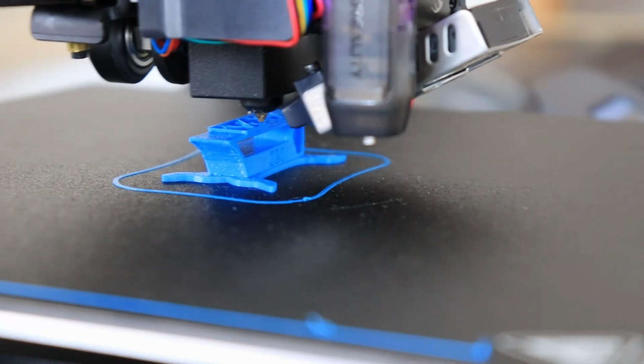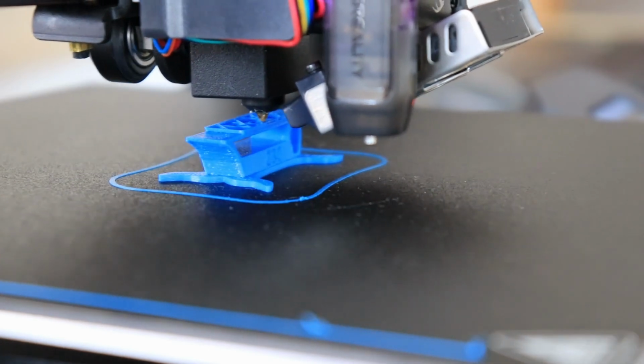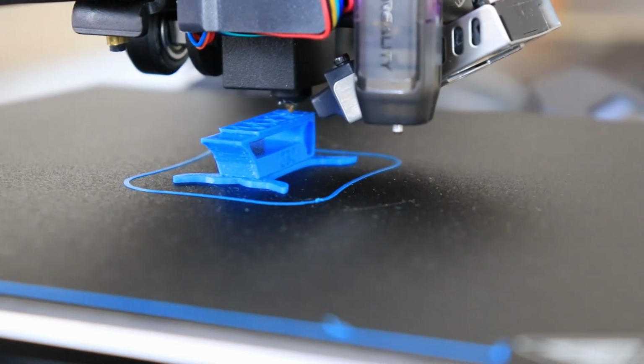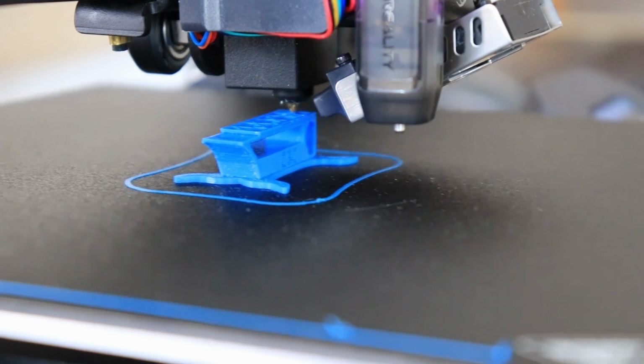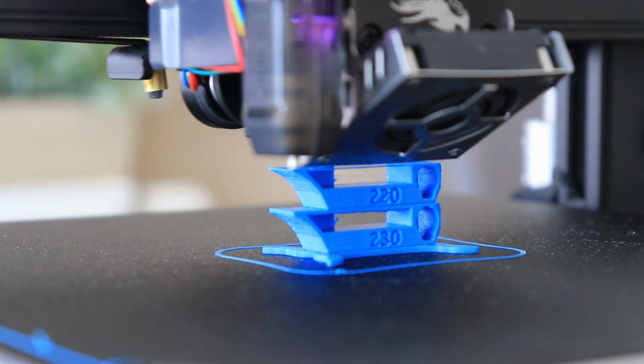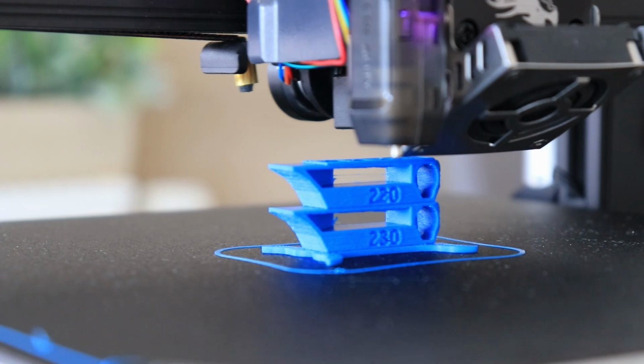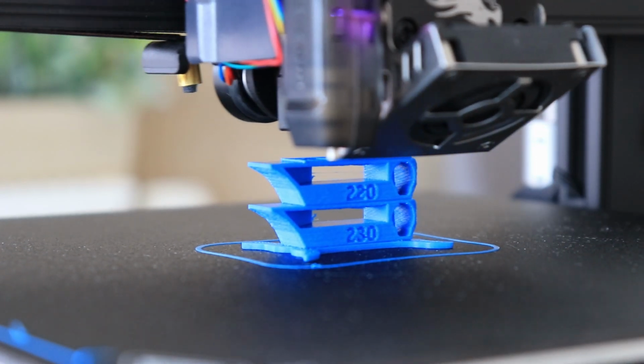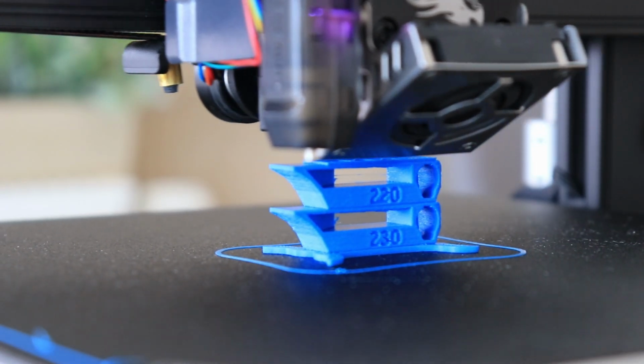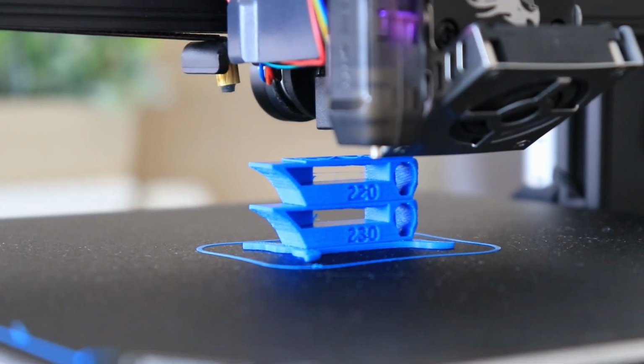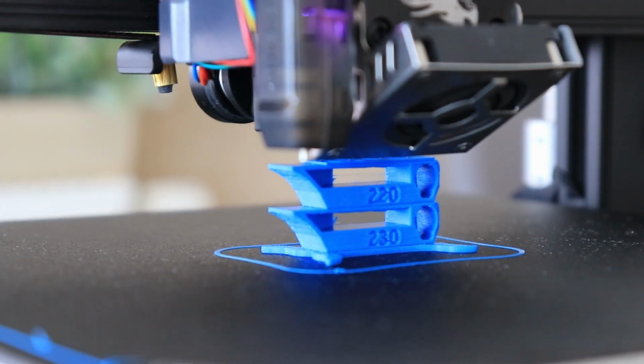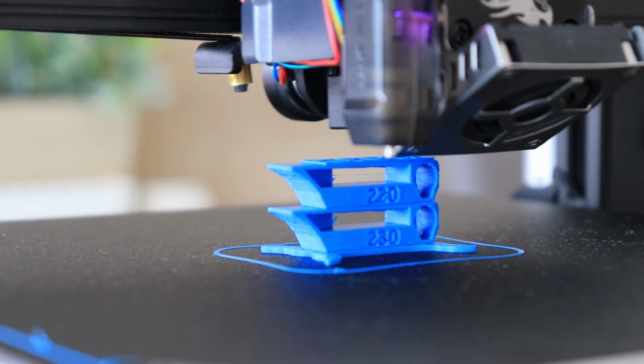The first element on 230 degrees Celsius is printed, and this printing is perfect like any other regular PLA would be. This is the bridging moment. This is the third element on 210 degrees Celsius. Interesting, I can see a little bit more string in 220 degrees Celsius, but on first tower that stringing was not there. But I will analyze this temperature tower later.